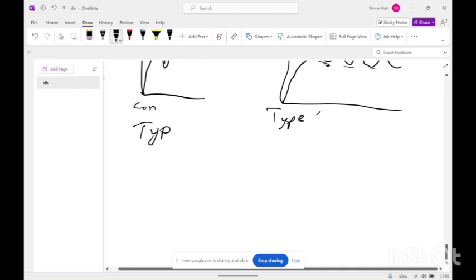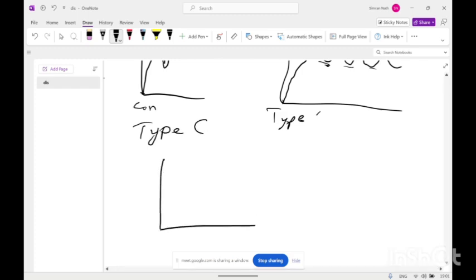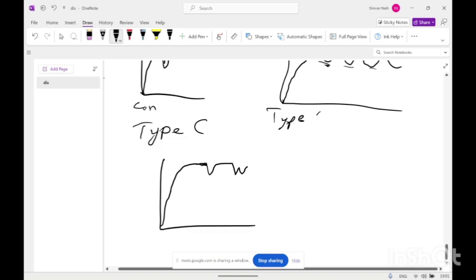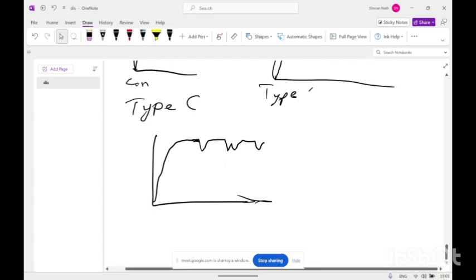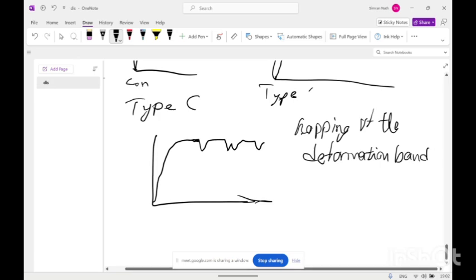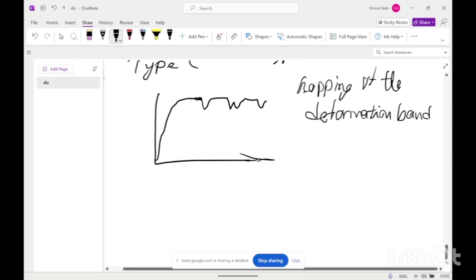While in the type C serrated flow there is a disrupted change in the stress. So this type of deformation resulted from the hopping of the deformation band from one position to another, means one serration can be defined as one hop. So one serration will form because of the one hopping of the deformation band.